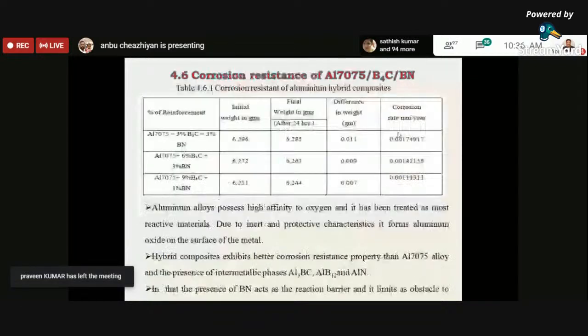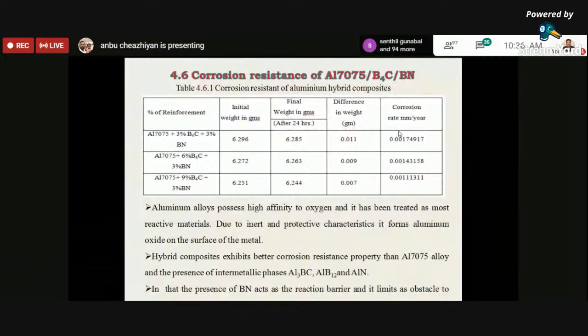So next we go for corrosion resistance. As you all know, aluminum alloys possess a high affinity to oxygen, and it is treated as a reactive material. So the presence of copper interacts with aluminum to form Al2Cu. So this acts as an obstacle for dislocation. This phase performs as a reduction of corrosion when the pH is increased. Owing to the disintegration of aluminum, the alloys through the surroundings act as a cathode. So this can be overcome by adding suitable ceramic reinforcement or harder ceramic reinforcement. So in these cases, we have added the harder and stiffer reinforcement along with the matrix alloys. So due to that, the corrosion properties of hybrid composites have significantly increased.